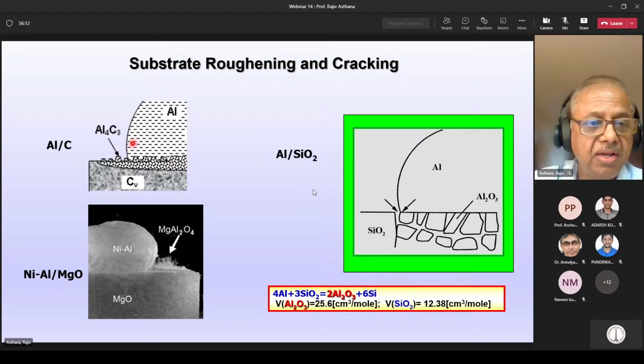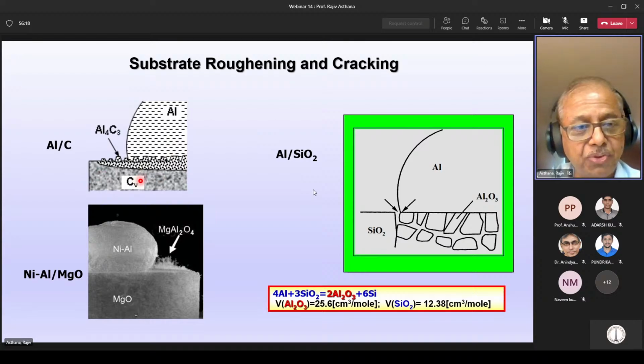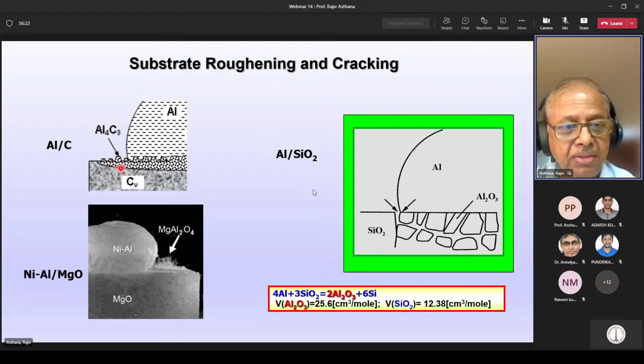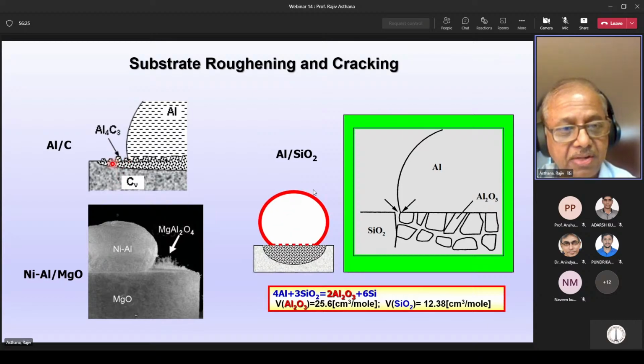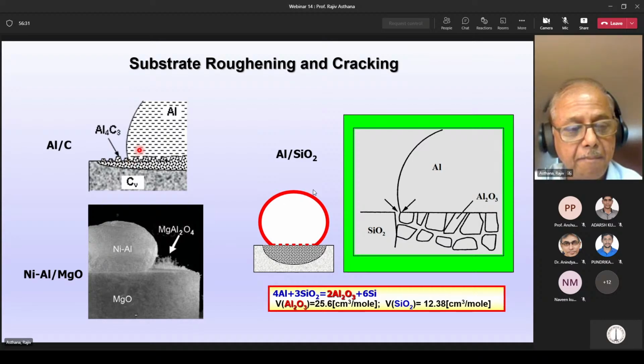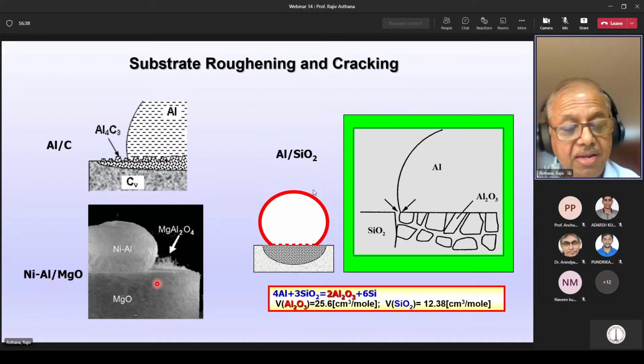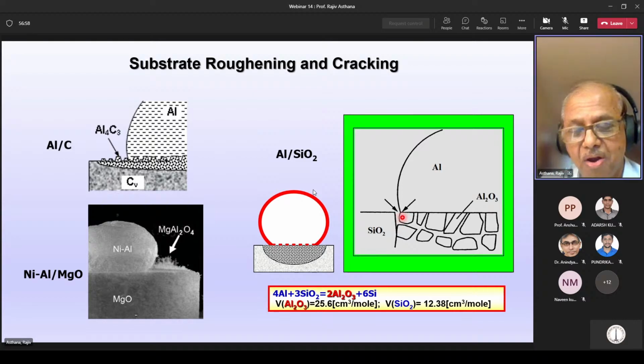Another example, aluminum carbon. A teeny liquid droplet of aluminum in contact with the vitreous carbon substrate. There is reaction, aluminum carbide formation, and these crystals form ahead of the liquid droplet. So the droplet is actually encountering a rough surface when it is spreading. In the nickel aluminum system, when nickel aluminum droplets spread on magnesium oxide, there's reaction and magnesium spinel forms like whiskers ahead of the droplet. In the aluminum silica system, for example, there is reaction between silica and aluminum, oxide forms, and there is volumetric expansion, which again causes cracking and roughening.